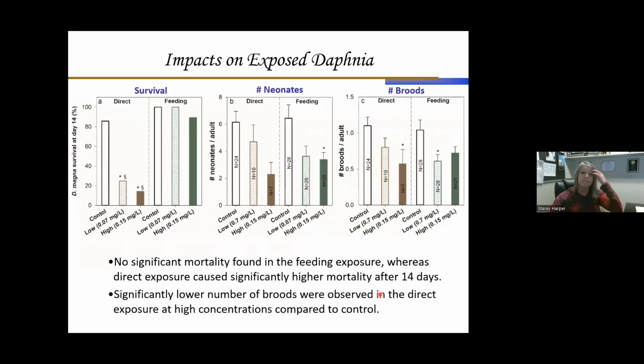Okay, so what are some of the impacts that we saw on Daphnia? This is survival. This next one is the number of neonates, and then the number of broods that were produced. And there was no significant mortality found in the feeding exposure, seen right here. But we did see a significant mortality after 14 days in these that had the direct exposure. We also see a decrease in the number of broods and the number of neonates that were produced during that 14-day exposure. And there was a lower number of broods observed in the direct exposure compared to control.